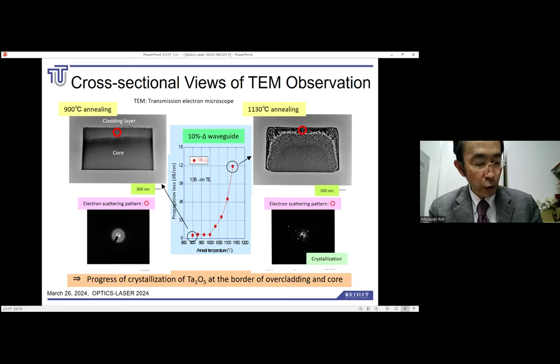Further examination of the electron diffraction pattern showed no problem in the 900 degrees Celsius heat treatment. However, a pattern indicating crystallization was observed in the 1,130 degrees Celsius heat treatment, indicating that crystallization progresses at the core overcladding boundary at this temperature, and that these crystallized particles are a factor in increasing the propagation loss. In devices made of quartz glass, the high temperature heat treatment process is necessary to densify and improve the quality of the glass film, so it is necessary to devise ways to prevent crystallization even after heat treatment.